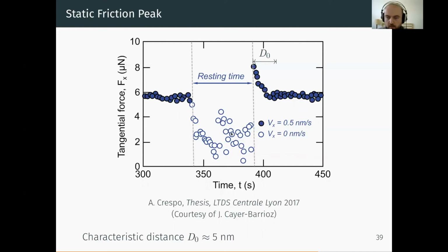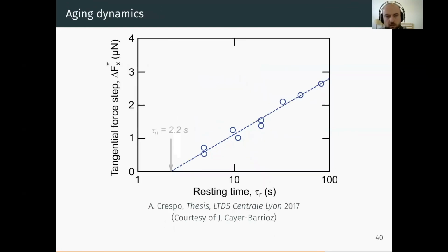And when they reslide, when they start sliding again, what they observe is an overshoot in the friction force. And this overshoot decays as a function of sliding distance over a distance that they measure is about 5 nanometers. What they also measure is the increase in this friction force, the magnitude of the overshoot, as a function of waiting time. And what they observe is a logarithmic aging of this overshoot in the friction force as a function of waiting time, for times that are above 2 seconds. For anything less than 2 seconds, they don't observe any overshoot in the friction force.